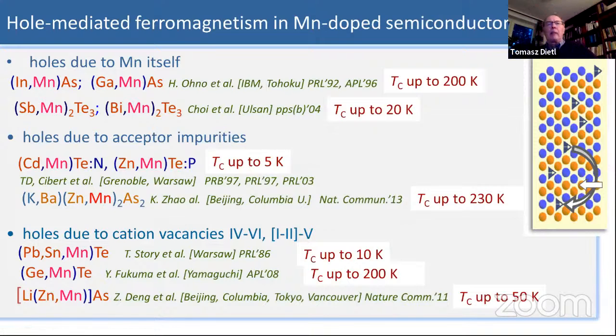Okay, this was samples without any carriers, in dilute magnetic insulators, but we all know that there are many materials in which we have holes, and these holes mediate ferromagnetic RKKY kind of interaction, ferromagnetic coupling between manganese localized spins. And these holes can originate from manganese itself. Manganese can be an acceptor, a shallow acceptor in some materials; as we said, gallium manganese nitride is a deep acceptor, but in many materials it's a shallow acceptor, doping the material with holes. These holes can be introduced by acceptor impurities in cases when the manganese impurity is neutral, divalent, replacing divalent cadmium, or these holes could be due to defects in many materials, like IV-VIs, for instance, where vacancies introduce a lot of holes, and these holes introduced by defects can mediate ferromagnetic coupling at various temperatures.